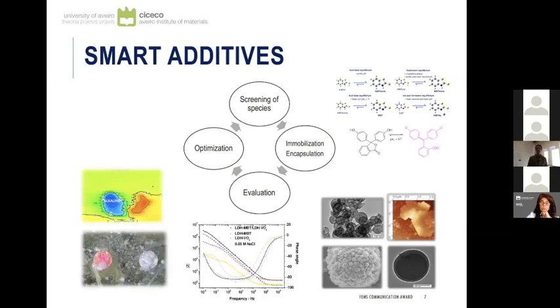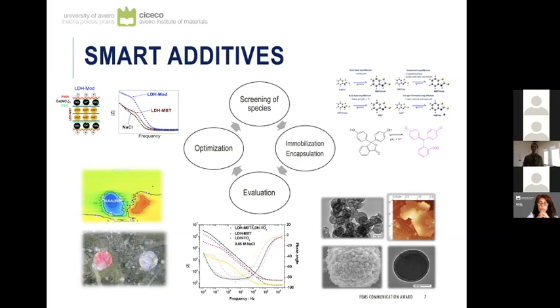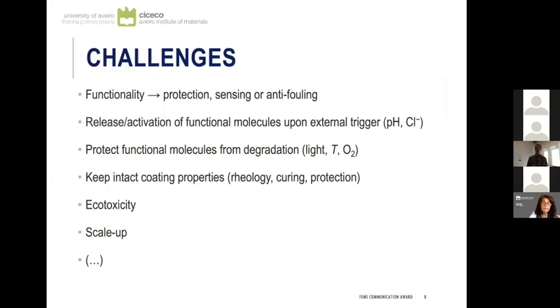We use different techniques, including electrochemical ones, as we have here in the examples, like electrochemical impedance or localized electrochemical techniques. And the idea is to see in the first stage if the modified materials are working or not. And of course, generally, we need to optimize the material. This can involve, for instance, the surface modification of the containers to change the triggering conditions, or co-immobilization of other active compounds. But in fact, this is not so straightforward.